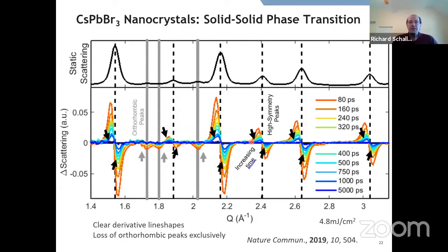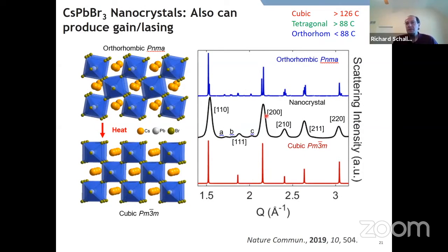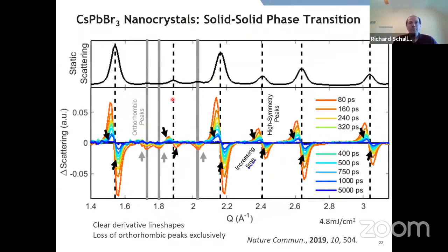And in studies of these, when we've done transient X-ray diffraction on them, one thing that we didn't really set out to see but saw is, first off, a peak that is present in both phases. So some of these features are essentially conserved for different crystal phases, and that's because these octahedra look about the same for the different crystal phases themselves. So those octahedral type of reflections, you just see beautiful derivatives, right?